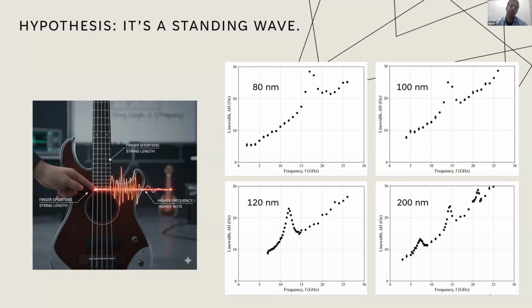But how can we prove that? Are we sure that this is standing wave? So we know that for a standing wave, the frequency of resonance is determined by the size of the cavity, which here is our film thickness. And if you look at our plots, you can see that when we make our film thicker, the bump frequency goes systematically to higher and higher frequencies. Furthermore, if you look at this 200 nanometer film, we see three bumps. It's like first, second, and third harmonics of this standing wave.